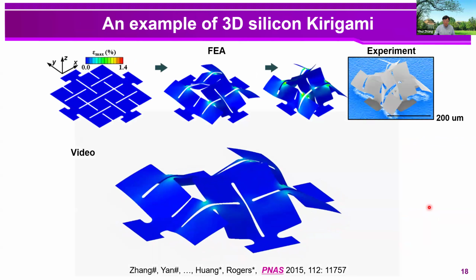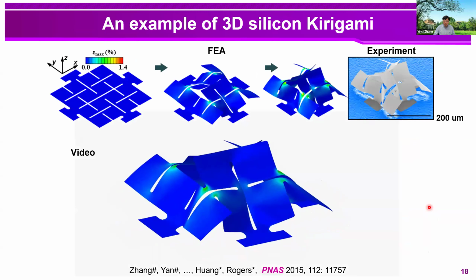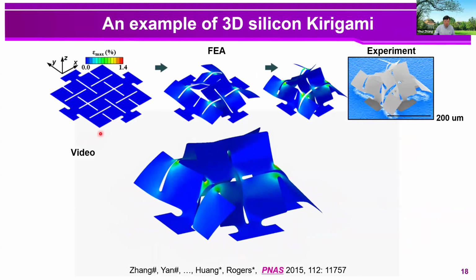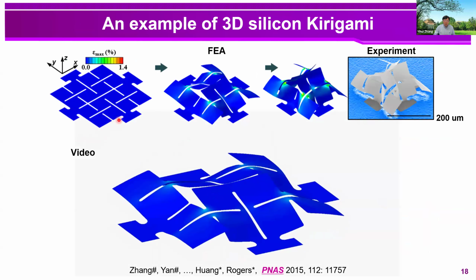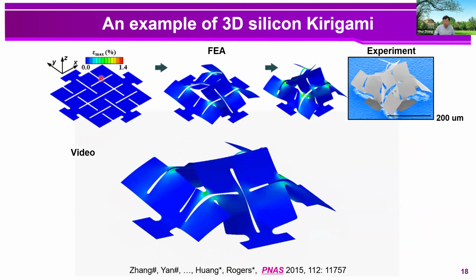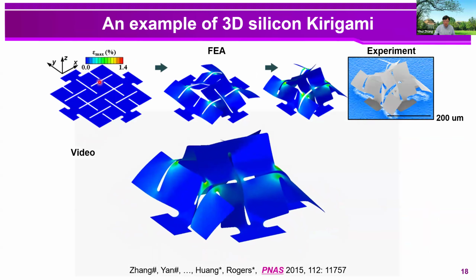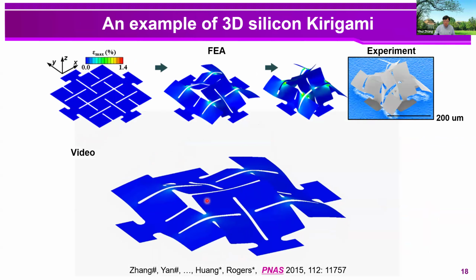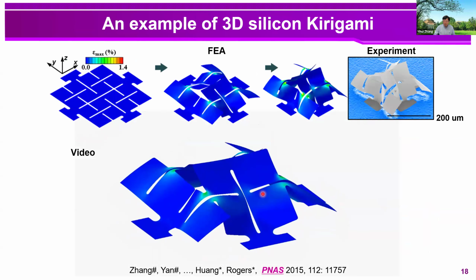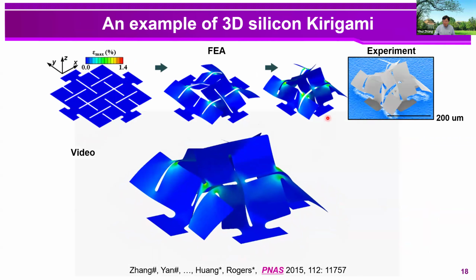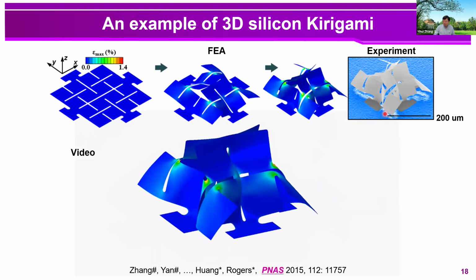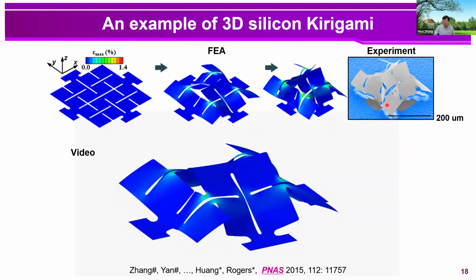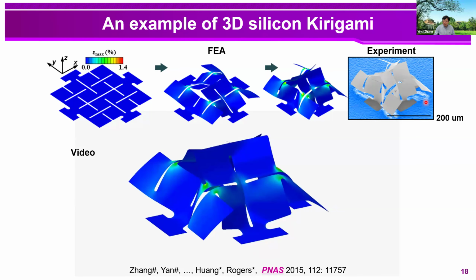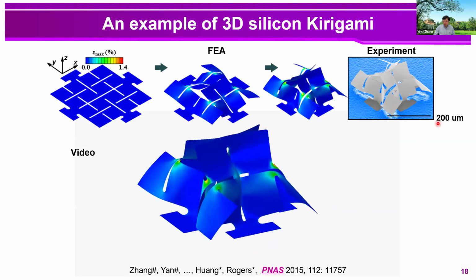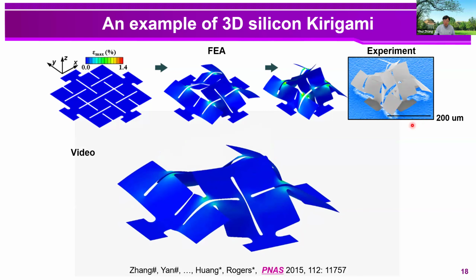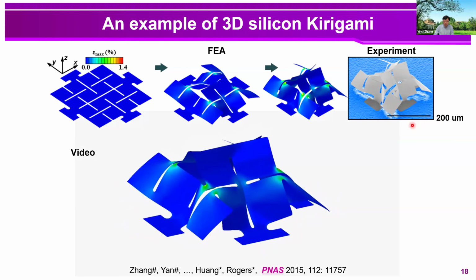Then let's look at an example of 3D silicon kirigami. In this example, we introduce a set of fractal crossing cuts that divide a large square into 16 small squares, which are interconnected with each other. This video shows a dynamic formation process of this 3D membrane structure. And this one shows the experimental results in single crystal silicon with a thickness of 300 nanometers. As you can see here, the lateral size of the entire structure is around 200 micron. So this is very difficult to achieve using previous approaches.